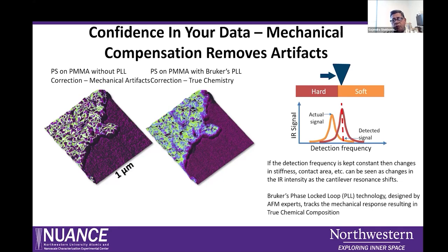So here the system uses the phase locked loop. If the probe is interacting with different regions of the sample which have different density variation, for example, there is a shift in resonance. So the phase locked loop gets activated and tries to maintain the cantilever resonance. That makes sure that we are getting the true chemical information just at the tip-sample interaction interface, not the variation because of maybe thermal or mechanical effects, or contact area differences.